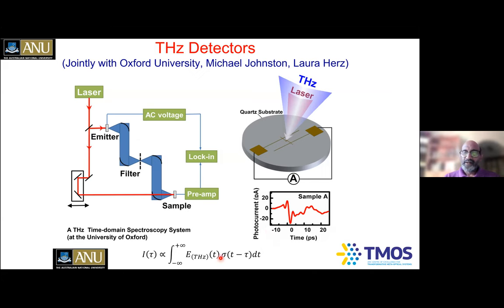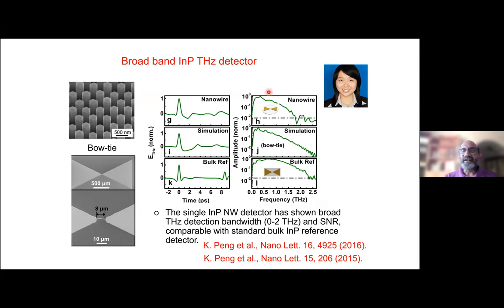So now, again, to cut the long story short, Kun Peng spent a lot of time during her PhD and demonstrated the first gallium arsenide nanowire terahertz detectors operating at room temperature, and later extended this to indium phosphide nanowire terahertz detectors. You can see she also makes use of these so-called bow-tie antennas. Our simulations have shown that these bow-tie antennas have a broader bandwidth than some of the designs which she had used earlier.